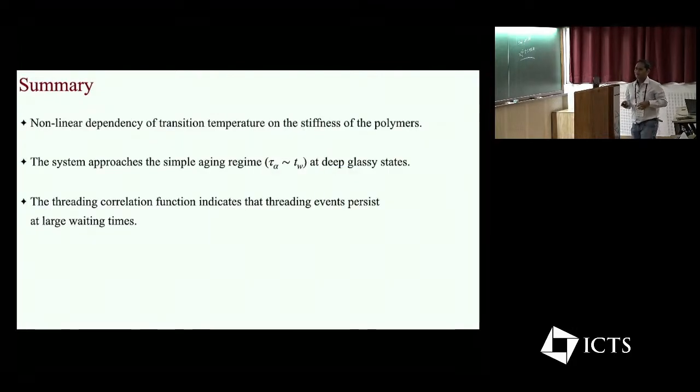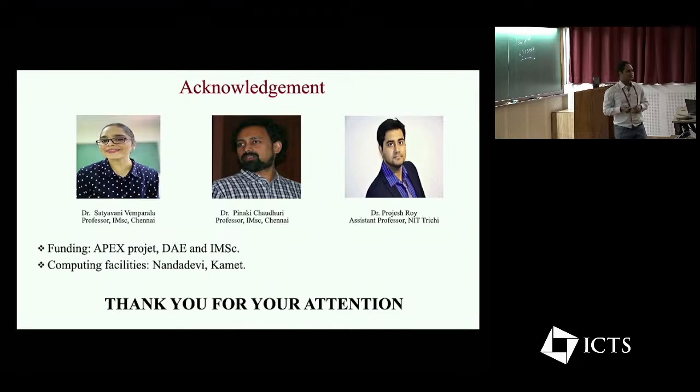Finally, to summarize, we observed a nonlinear dependency between the transition temperature and the stiffness of the polymers. Deep in the glassy state, the relaxation time approaches linear dependence on Tw, so it is a simple aging regime. We also see that threading events persist at temperatures much below the transition temperature. Finally, acknowledgements, and thank you for your attention.